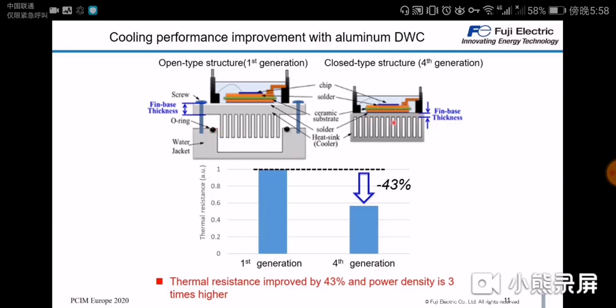In our fourth generation, you can see there is no gap between the top and the bottom. So the fin base and the water jacket are one part, and also the internal structure has no gap as shown in here. So the water cannot bypass below, and every bit of water running through the cooler is directly used to transfer the heat away. Also, you don't have any leakage issues because it's all one solid connection. We were able to reduce the thermal resistance by 43% compared to the first generation and increased the power density by a factor of 3.